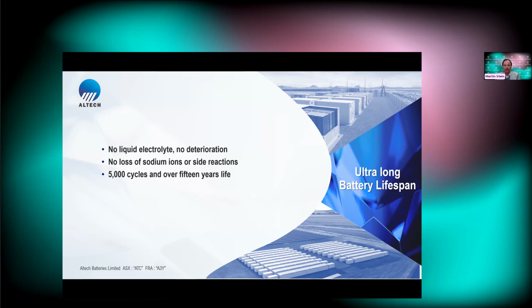And we don't have the liquid electrolyte and the lithium degrading. Sodium does not degrade. In fact, there's some independent testing that shows that it actually improves with cyclability, but it certainly doesn't degrade, and these batteries have a life cycle of over 15 years.